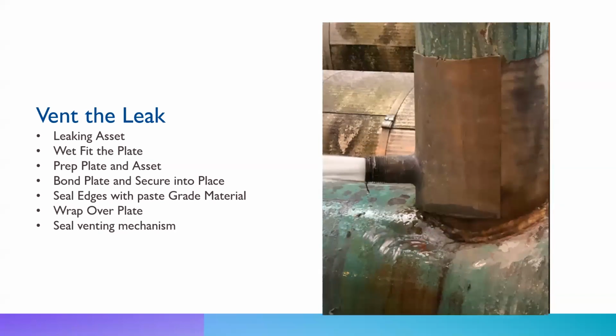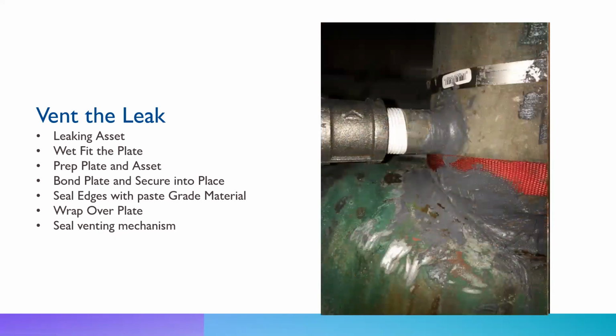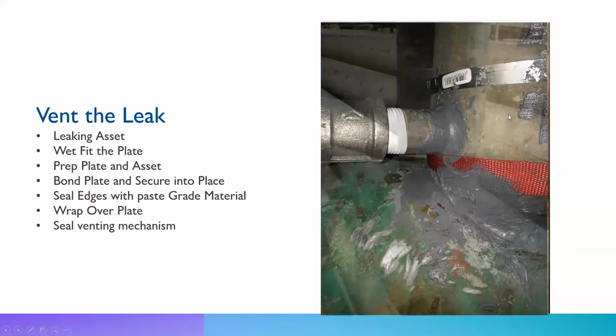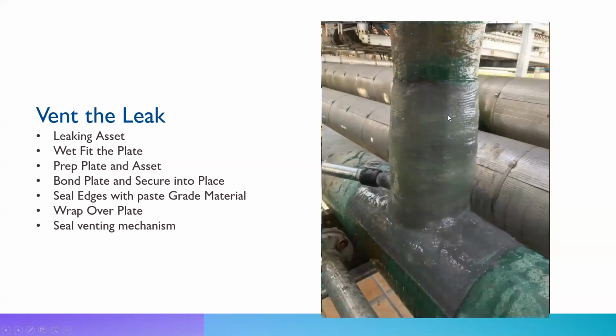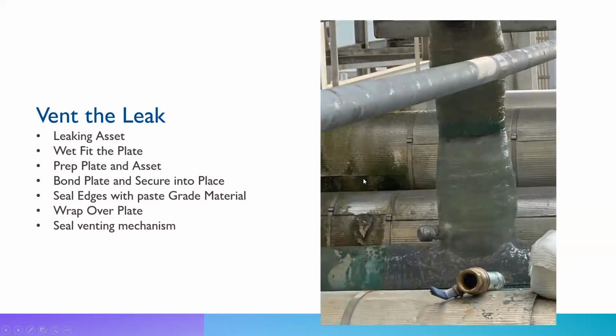So here we did a quick fab at our shop with some simple thin gauge metal welded on the nipple and dry fit it in the field. Good to go. Bonded it down, put on a coupling with a hose to collect all the water coming out. Once this was set up, we were able to wrap it with our fiberglass composite. And once everything cured, we were able to cap off the top.